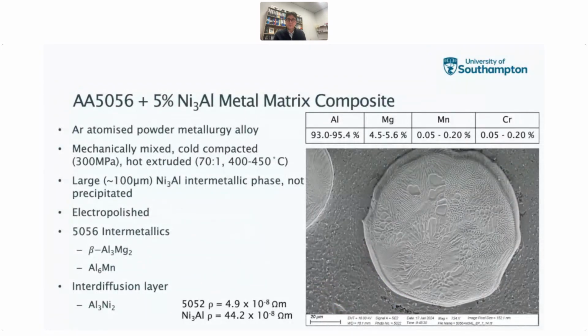So a little bit more information on the materials we used. So this is the metal matrix composite. It's an argon atomized powder metallurgy alloy. So it's a work hardening 5056, and that will be mixed with 5 weight percent Ni3Al phase and then cold compacted prior to hot extrusion. And the reason we chose this is because you can see that the particles are very large. We get very distinct large particles, about 100 microns across. So it's very easy to identify where these were laterally and position accordingly. We did consider looking at some stainless steels and the carbides, but we generally found that the carbides are quite small and a bit difficult to locate.